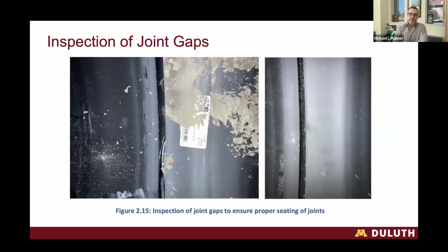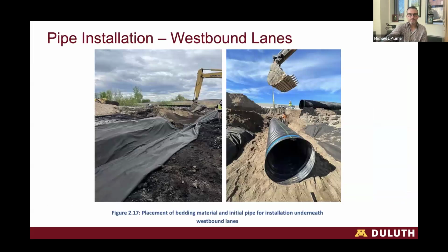We inspected the joint gaps after installation. So you can see these are very, very small joint gaps. Corrugated high-density polyethylene pipes and polypropylene pipes, for that matter, can have a fairly large joint separation and still perform well. The joint design is quite a bit different than that in concrete pipes. But typically we like to make sure that these pipes are homed at installation, and these were all installed very well from a joint standpoint.